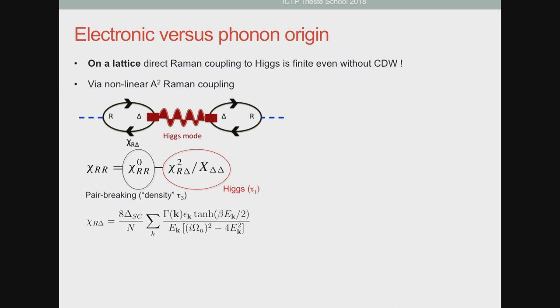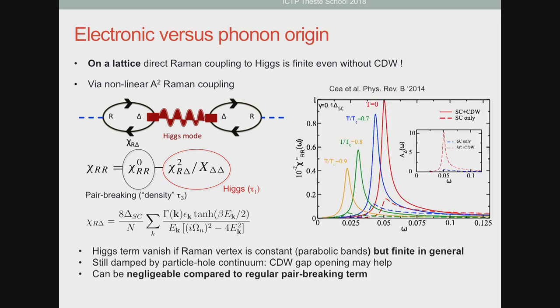And usually, gamma k is the Raman vertex, essentially this coupling between light and electrons. In the literature, and in particular if you look at Varma's paper, he would take this essentially as a constant, k independent. And because of particle-hole symmetry, because there is only epsilon k here, this vanishes. But you can really clearly see that as soon as you put some k dependence in the Raman vertex, there is no reason for this to vanish. So actually, and I think this is something that was overlooked, the direct coupling, not even thinking about the charge density wave phonon, is actually finite. Now, the question is how big it is.